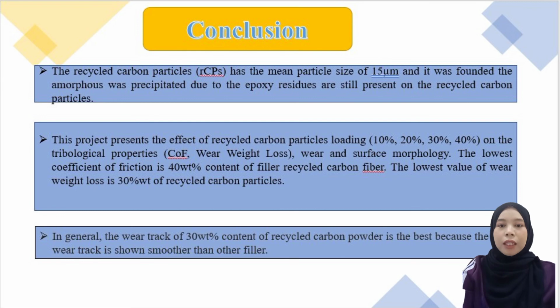In conclusion, the recycled carbon particle has a mean particle size of 15 micrometer, and it was found that the amorphous phase was precipitated because epoxy residue is still present on the recycled carbon particle. This project presents the effect of recycled carbon particle loading of 10%, 20%, 30%, and 40% on the tribological properties, which are coefficient of friction, wear weight loss, wear, and surface morphology.